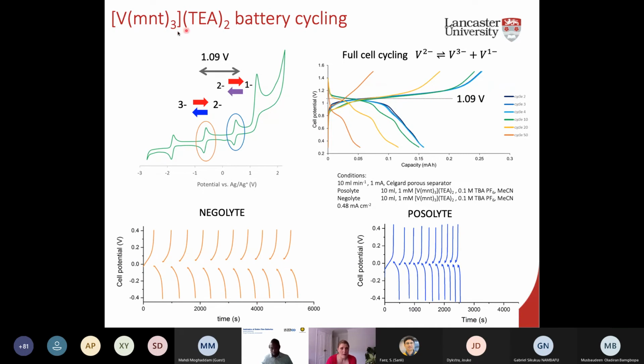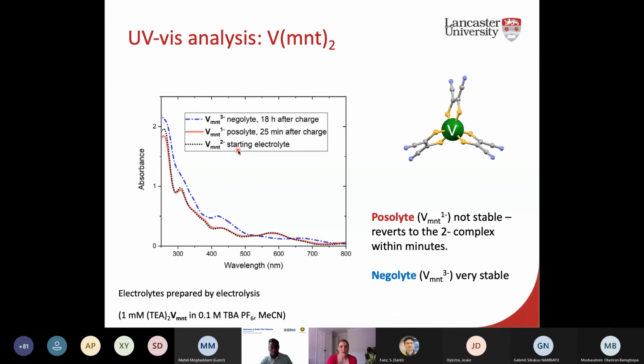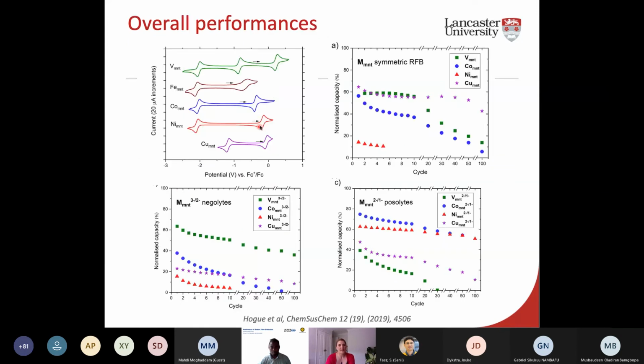And what we found for this vanadium complex, for example, is that when we looked at the stability of this species cycling on its own, we've got a very nice stable couple compared to when we're looking at this species where we see that decay. So that decay is largely driven by this loss because this positive species is unstable. And we verified that using UV-vis, where we saw that the positive solution was reverting back to its original state after being charged. So while things look good on the voltammetric scale, they don't necessarily last and persist when you're going into a flow cell system. But being able to evaluate that effectively is really challenging.